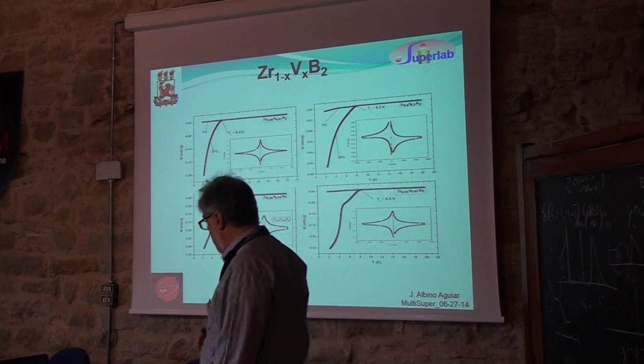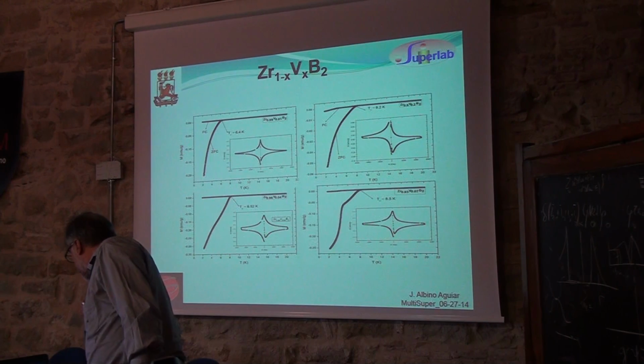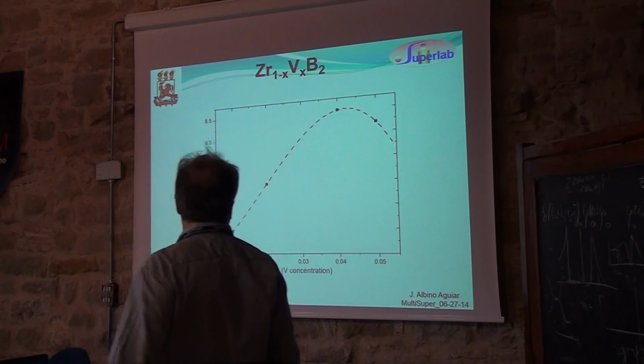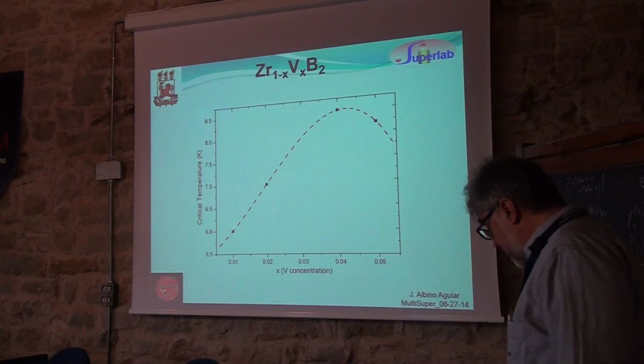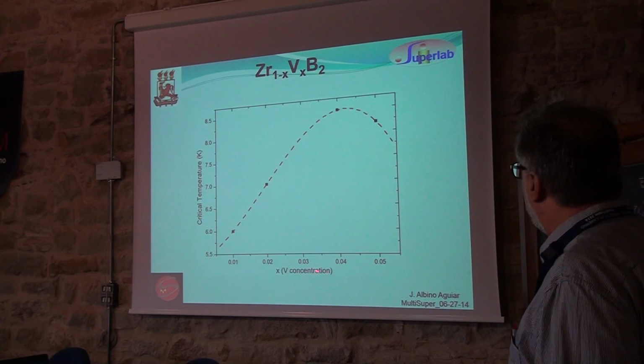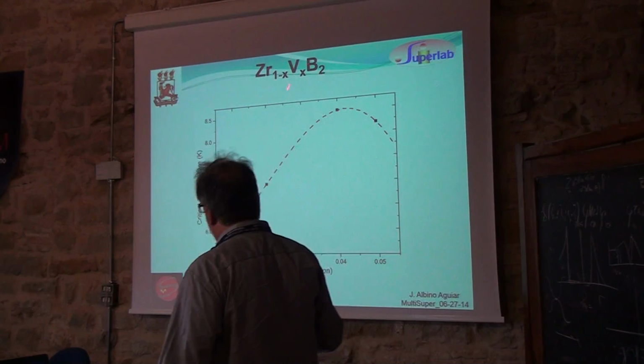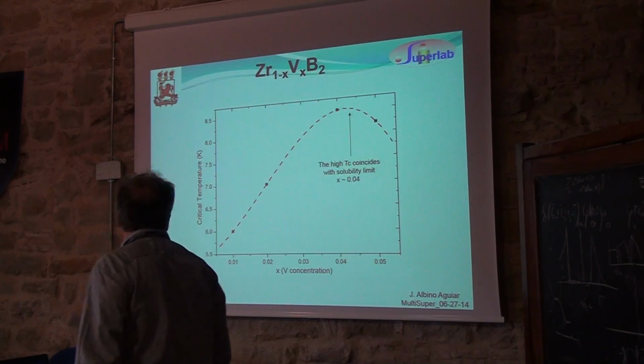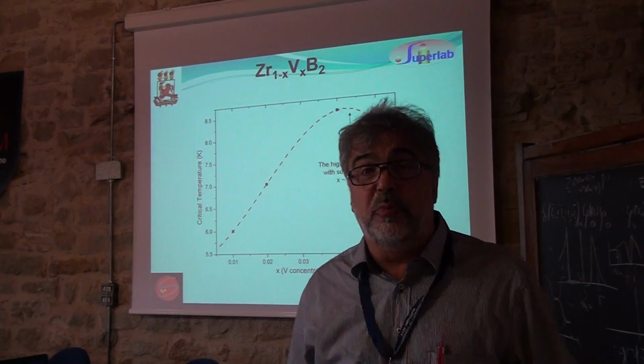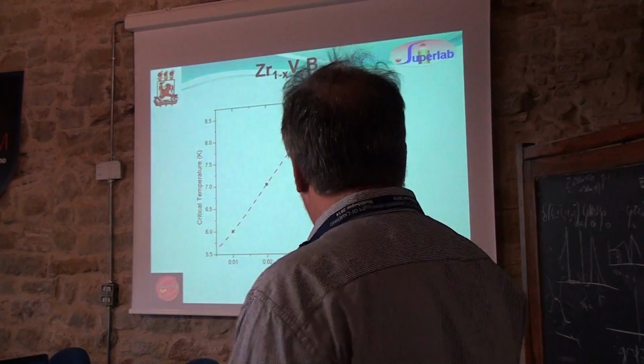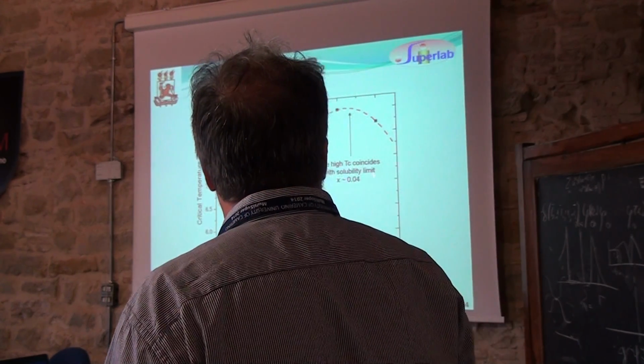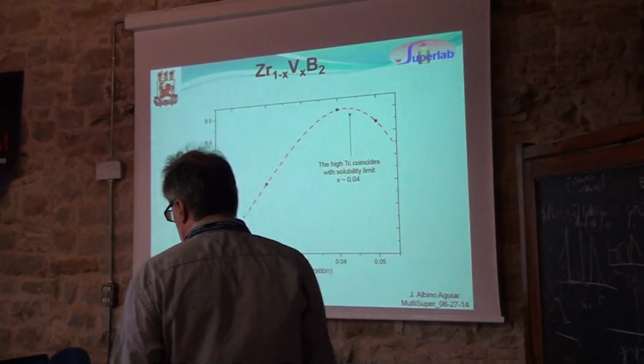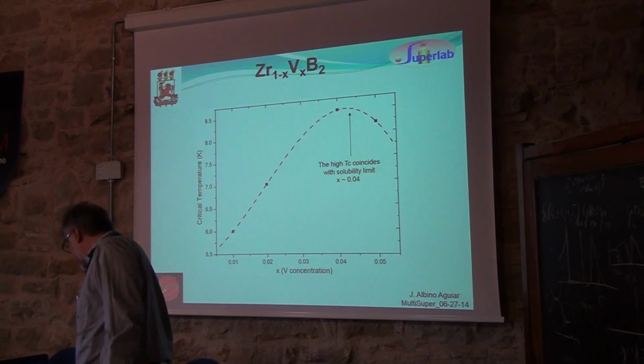We did not identify this. But if you draw the critical temperature as a function of concentration, you see that there is a maximum that coincides with the solubility limit. So we decided to look at this sample in more detail.